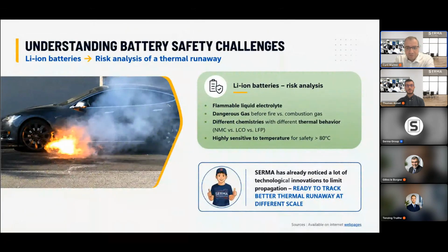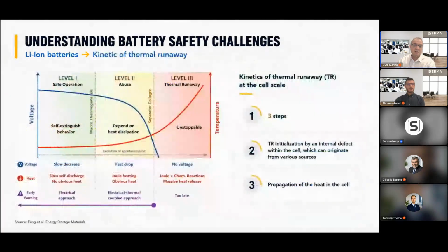Something very important is that it's sensitive to temperature. For safety, from 80 degrees you can start to be a bit afraid. The electrolyte is sensitive below that, but for safety it starts at around 80 degrees at least. At SERMA, we are very much into it. We test a lot of packs, and we follow the technological innovations placed in the different systems in order to avoid and limit this propagation. This is something very common at SERMA.